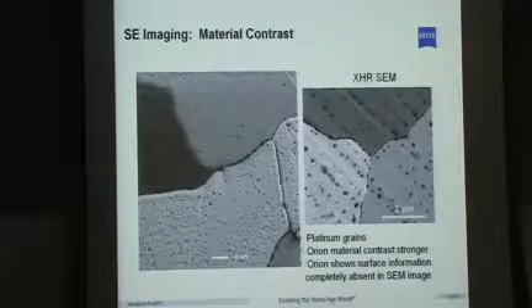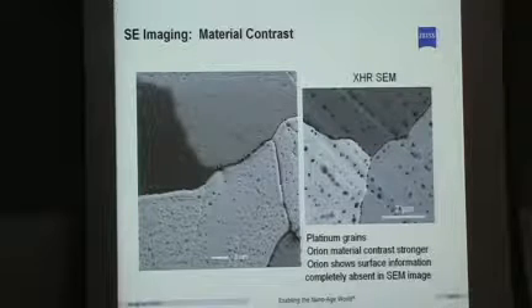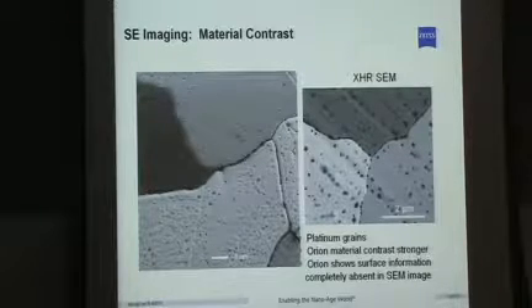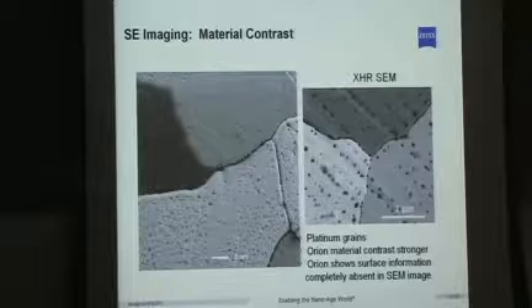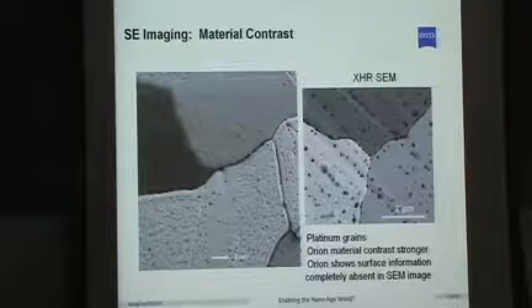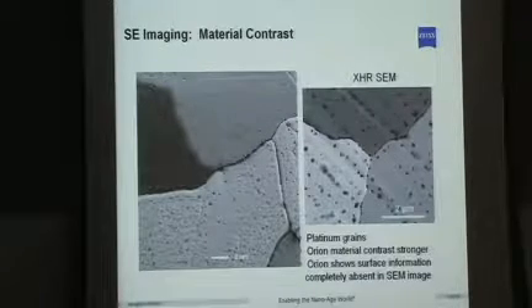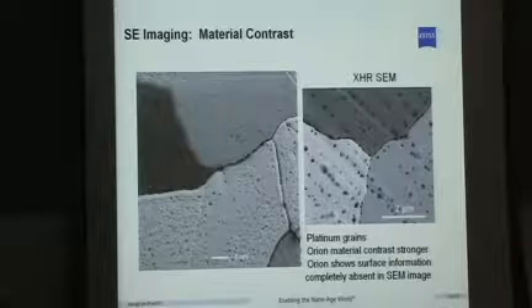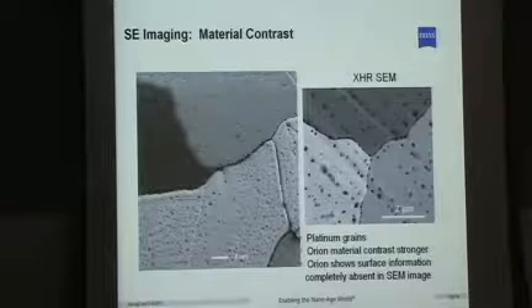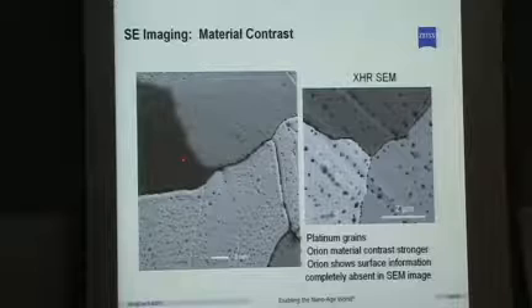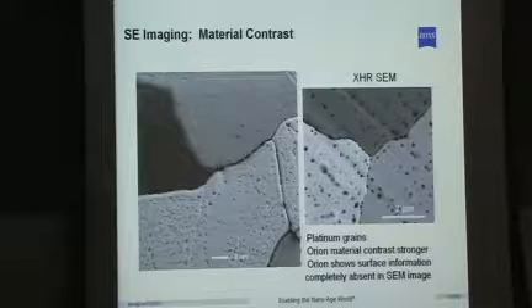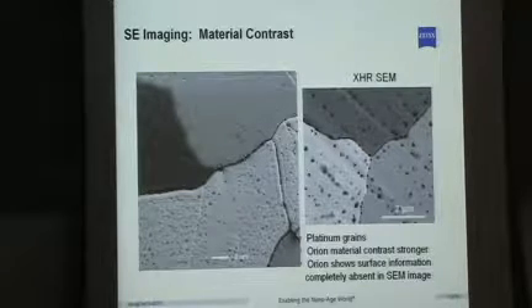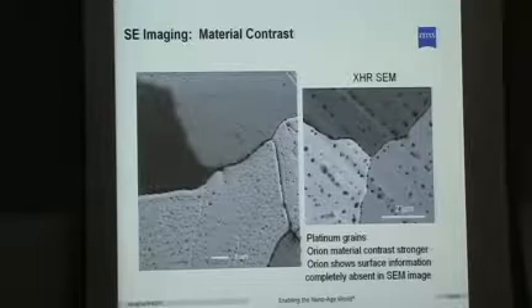This is an image of platinum, and you can see right away these are different grains of platinum, different crystallographic orientations. I'll explain that in a second. And this is a comparison SEM image, and you can see the grain contrast from one grain to the other, but you don't see the fine texture here. You can see little atomic terraces on these samples, which really shows you the kind of surface information that we can get.